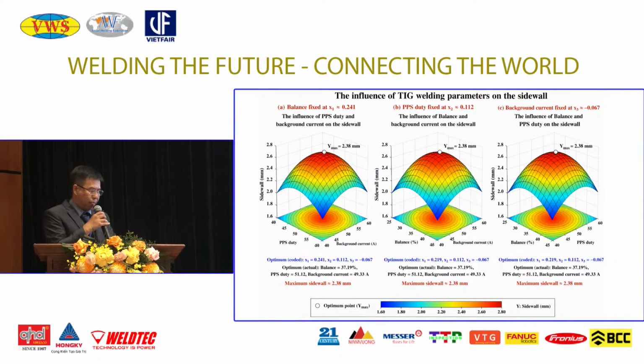The interaction between pulse frequency, background current, and balance is evaluated by fixing one parameter at its optimized value, based on the result of 6061-T6 aluminum weld using Hongky 350 RS Pro. The variation of the other two parameters is analyzed in relation to sidewall penetration.